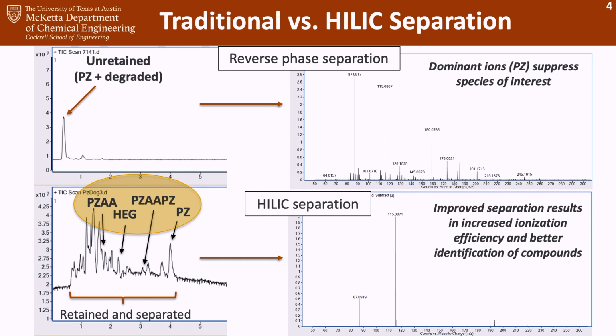And so therefore, once you send the solution to the MS, you get a huge smattering of peaks and very little separation, which makes ionization efficiency very low, and therefore makes detection very difficult. Another thing is that piperazine, being one of our most dominant species, is going to take up much of the competitive ionization efficiency from the MS, also reducing detection.